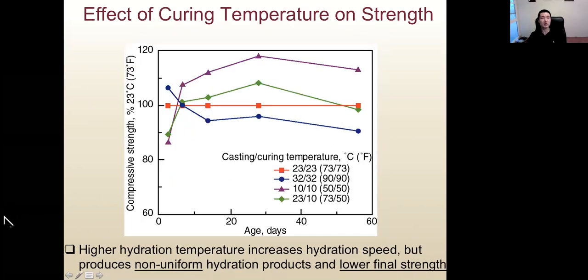And this slide shows us the effect of curing temperature on strength. Again, all these four concretes have exactly the same mix design. The only difference is the casting and curing temperature. For example, the red one means the casting temperature is 23 degrees Celsius or 73 degrees Fahrenheit, and the curing temperature is the same, 23 or 73 Fahrenheit.